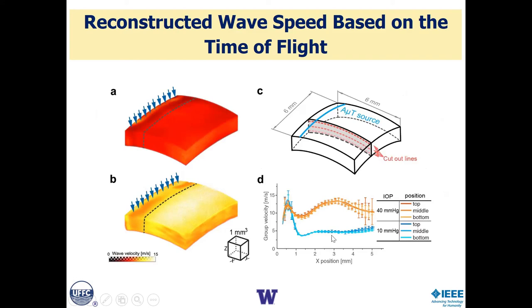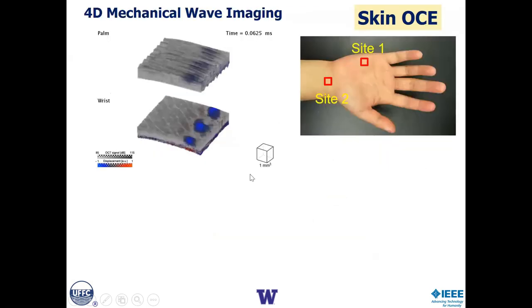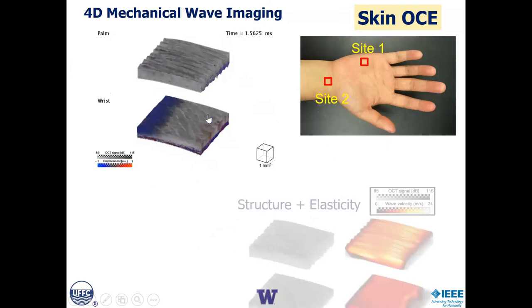We see a much lower wave speed at the low pressure versus the high, and this is very understandable because soft tissue, especially collagenous tissue such as the cornea, is very nonlinear acoustically. So the shear wave or the mechanical wave speeds will change quite a bit depending on the pressure, and this was demonstrating this. So very cool. We then did this in the skin, and you can look here just contrasting something in the palm versus the wrist. Okay, here's the palm with the Langer's lines and the wrist. You can see much faster wave speeds in the palm than the wrist due to the elastic characteristics.